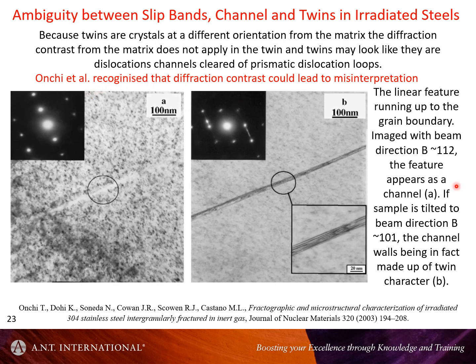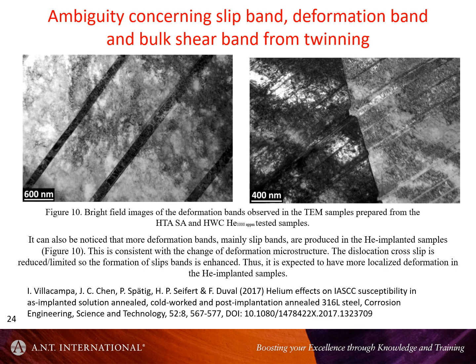2003, and realized that you have to be very careful because here is an apparent dislocation channel. It looks like the loops have been swept up in this channel because there's no contrast there. But that's simply because there's no contrast, because this is a twin, and Onchi and company showed that, yeah, there's your twin. So this ambiguity is clear in this case that it's a twin. So, be careful of reports when somebody sees that and then says, oh, well, that's a channel, because it isn't. Here's another example where there's ambiguity, but the authors left it ambiguous.